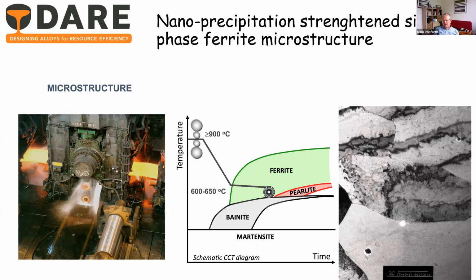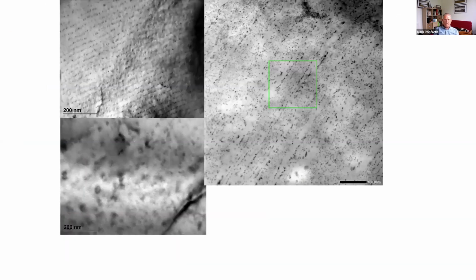So that's the image on the right, which is just showing the ferritic structure in a transmission electron micrograph, and you can just about make out these very fine precipitates that are there. If we look in more detail, we can see these beautiful rows of precipitates, there's just 3 examples altogether there. And they are typically in the region of 3 to 10 nanometers in size.